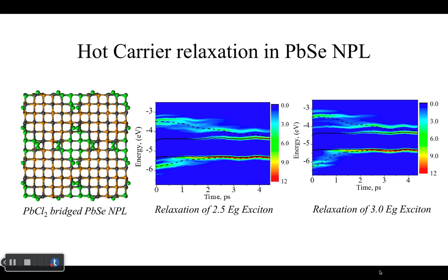Before we go to the next slide, did you look at the nonadiabatic coupling, the magnitude for occupied and unoccupied states? Because that could also lead to very slow relaxation. Yes, I haven't put it on the slide presentation here. That was showing the hot hole. The occupied state has almost 1.5 times bigger coupling constant compared to the unoccupied state.